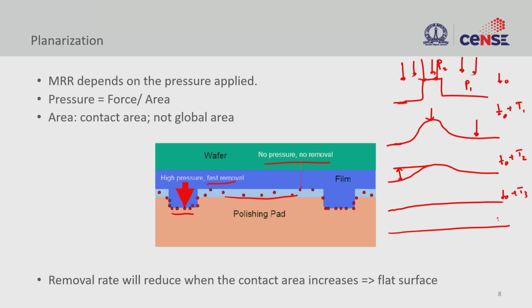And then if you keep on doing it, so let's say I want to even do longer duration polishing, then you are actually slowly removing this whole profile. So this whole profile is going to move down, but the flatness will remain. So you will lose material, okay. So if you can stop at this time, then you will get reasonably flat without loss of material, right.